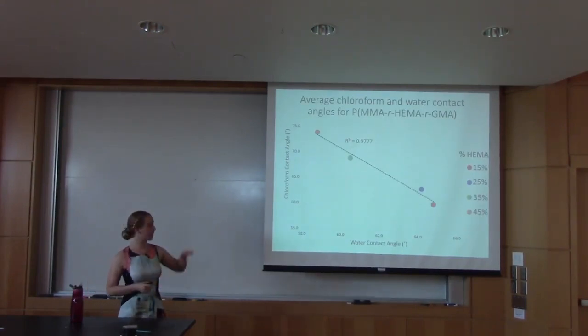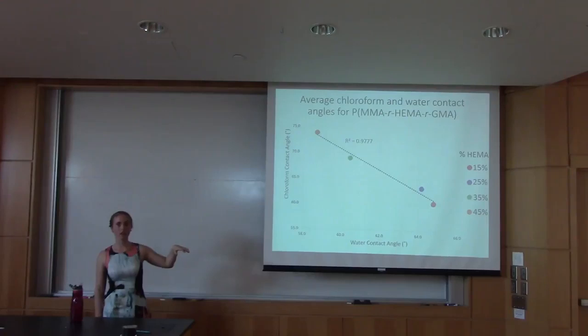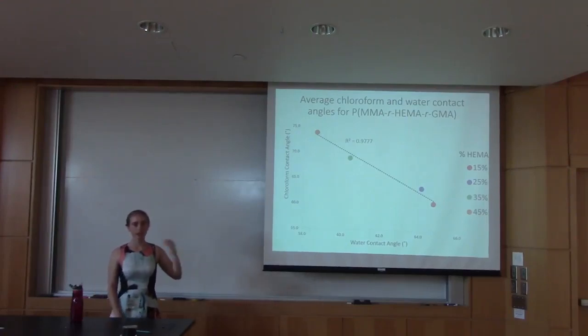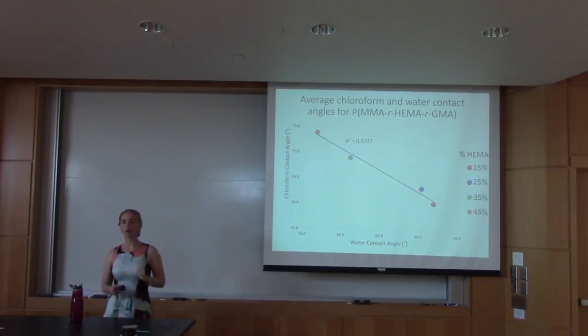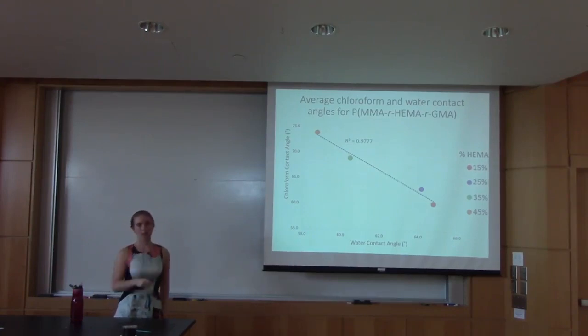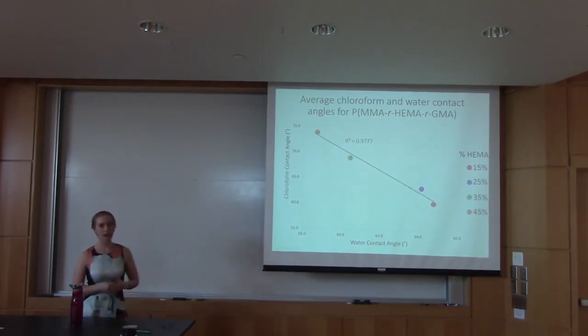So this just shows on the x-axis our water contact angle, showing how hydrophilic our measurements are, and then on the y-axis we have our chloroform contact angle, which is how hydrophobic. And we are decreasing the amount of HEMA from top to bottom. And so we have a pretty decent trend, a pretty decent R-squared value from this.